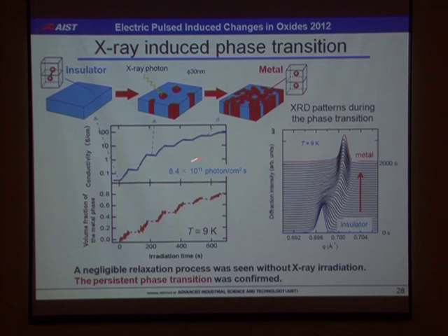And deducing from the metallic volume fraction, we can conclude that one X-ray photon creates a metallic pad with a diameter of approximately 30 nanometers. Namely, how does it decay with time if you stop the radiation? It's a constant, no change. It does not decay. Why is that? This is because this is persistent phase transition. And of course, at high temperature, we can see the relaxed behavior, but at low temperature, no decay. Actually, such metallic pads are connected to each other, and finally, the metallic state is seen.